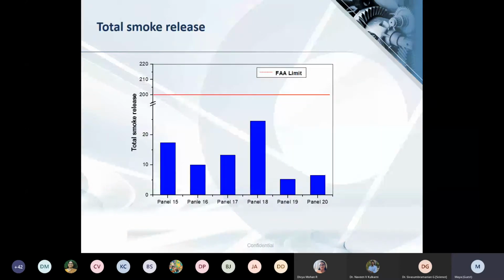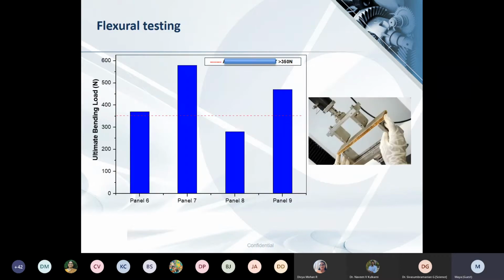Then as per FAA limit, the total smoke release should be 200 or less than 200. So as you can see, all the panels are complying with the limit. In terms of flexural testing, the requirement was that the ultimate bending load should be greater than 350 newtons. And then you have here most of the panels meeting with that requirement except for panel 8.